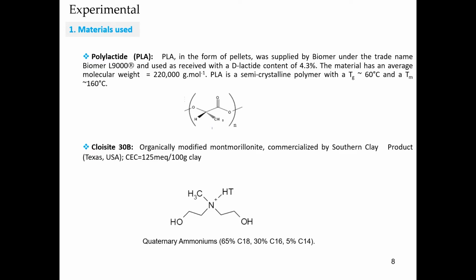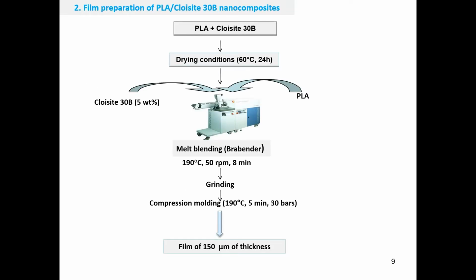Briefly, I will show you the materials used. Polylactide PLA from Biomer, and also the Cloisite 30B from Southern Clay Products as the manufacturer. Here are some processing steps to prepare the PLA Cloisite 30B nanocomposite and also the neat polymer through the use of a Brabender to mix in the melting state our nanocomposites with 5% of Cloisite 30B and the PLA, while compression molding was used to prepare films of an average thickness of 150 micrometers.